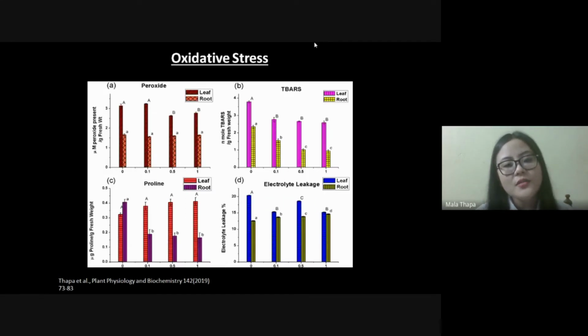Now, hydrogen peroxide plays an important role in plant stress mechanism. In optimum concentration, hydrogen peroxide acts as signaling molecule involved in triggering and signaling cellular growth. But at high concentration, hydrogen peroxide induces oxidative stress and programmed cell death in plant. In our study, you can see there was no significant alteration found in any treatment. And the peroxide content in both leaf and root were in optimum range, which indicated that due to zinc sulfide treatment, peroxide content remains in optimum range and it acts as signaling molecule for the plant growth. This could be a reason for enhancement of growth in mung bean plant.